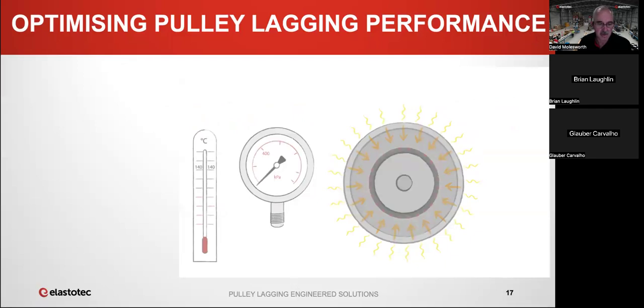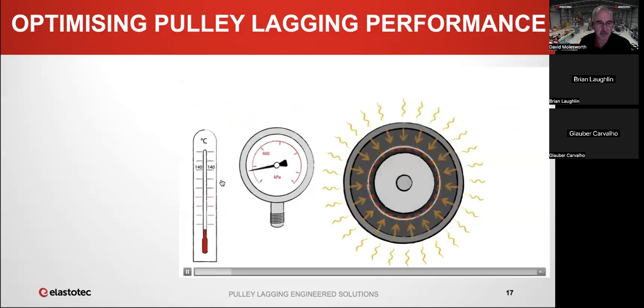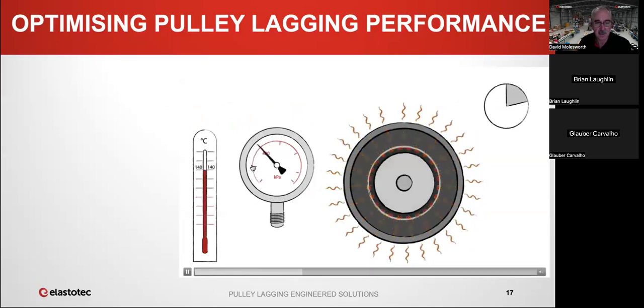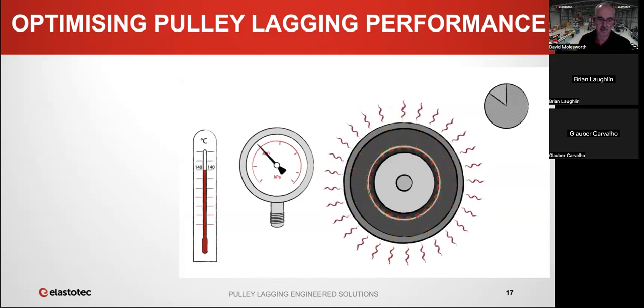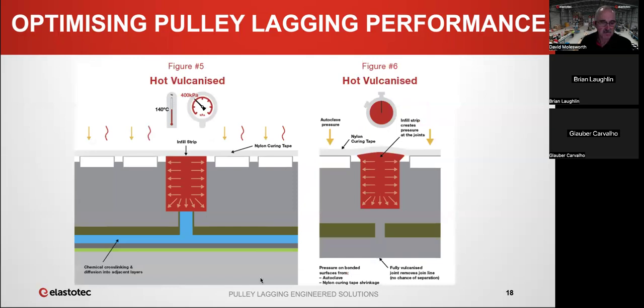This is just another graphic to show the curing process. So temperature goes up to around 140, with 400 kilopascals of pressure. It's inside the autoclave for between 3 and 6 hours, depending on the size of the pulley. This graphic's basically showing the same thing. The end result here is that all of the joins and separate pieces have combined into one, and this makes the whole lagging system very, very robust.